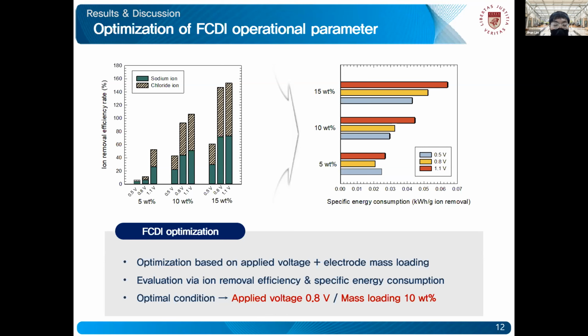So as we can see from the figure on the left that shows the ion removal efficiency rate according to applied voltage and electrode mass loading, we can see that the removal rate continuously increases with increased applied voltage and electrode mass loading. However, as I previously explained, having a higher electrode mass loading also increased the electrical current of the system, which also leads to the increase in the specific energy.